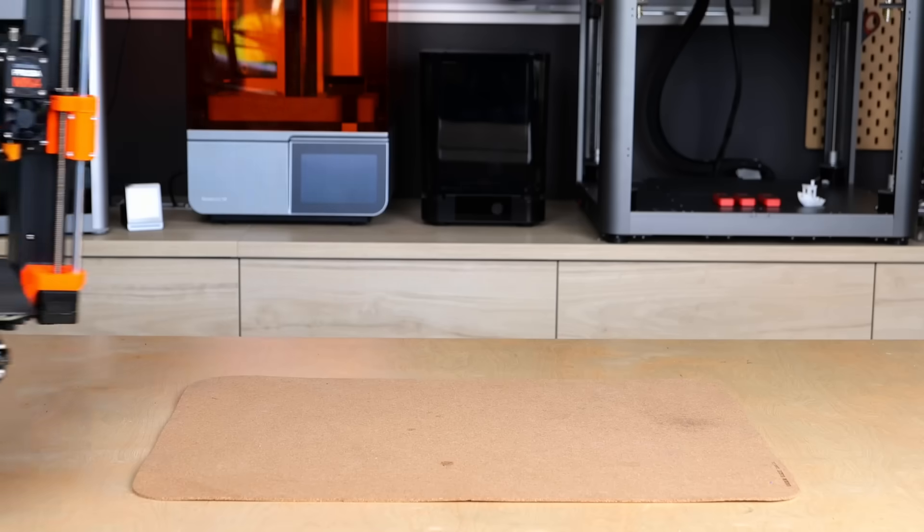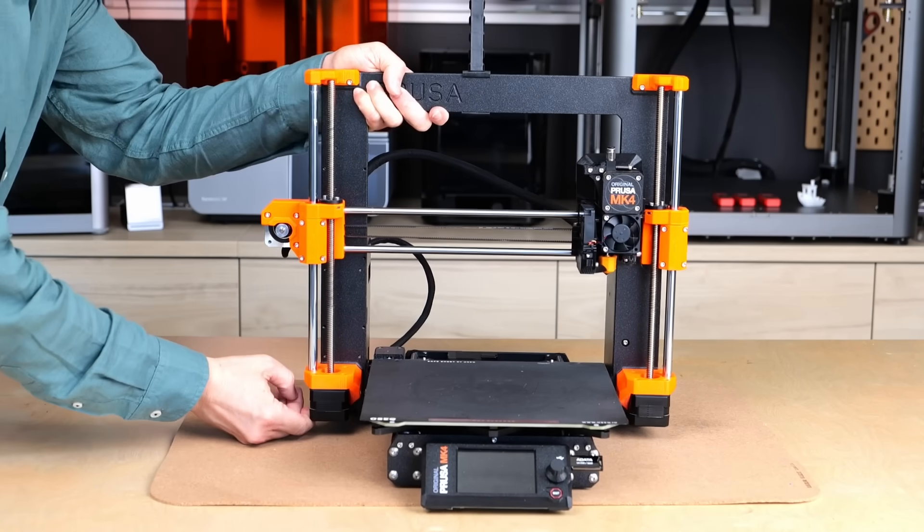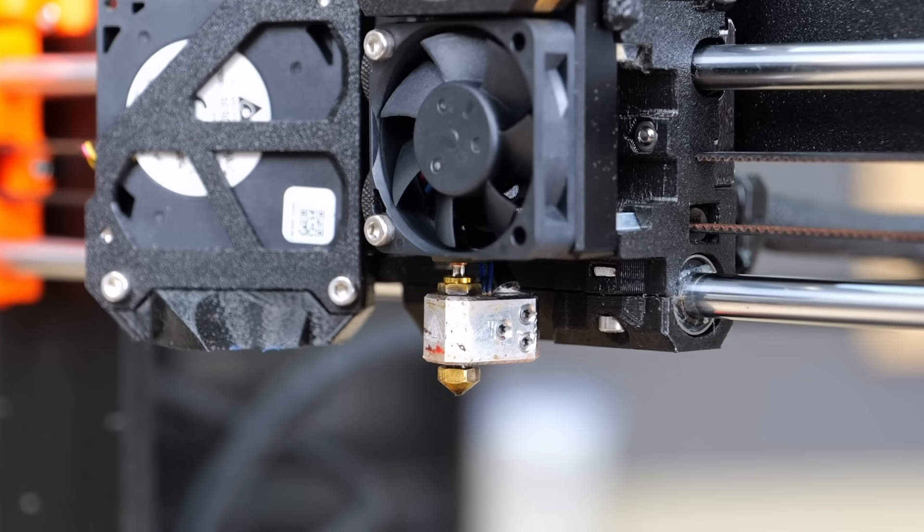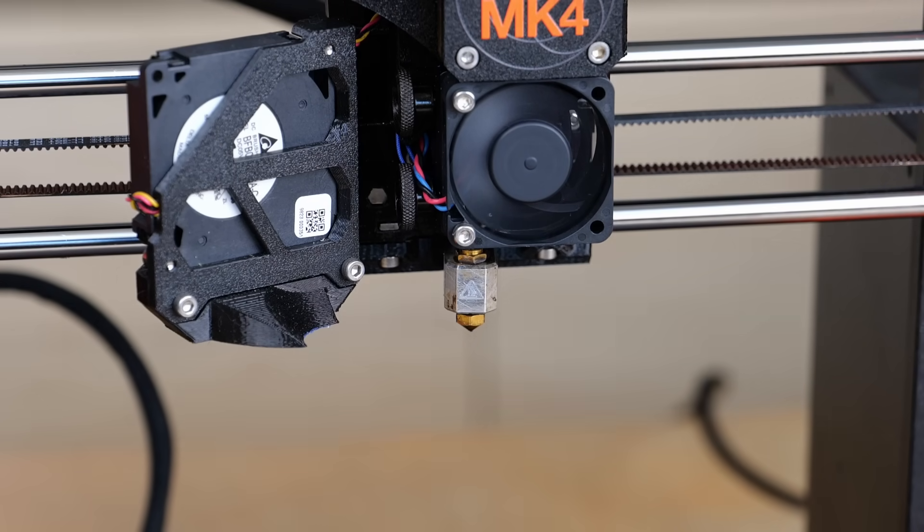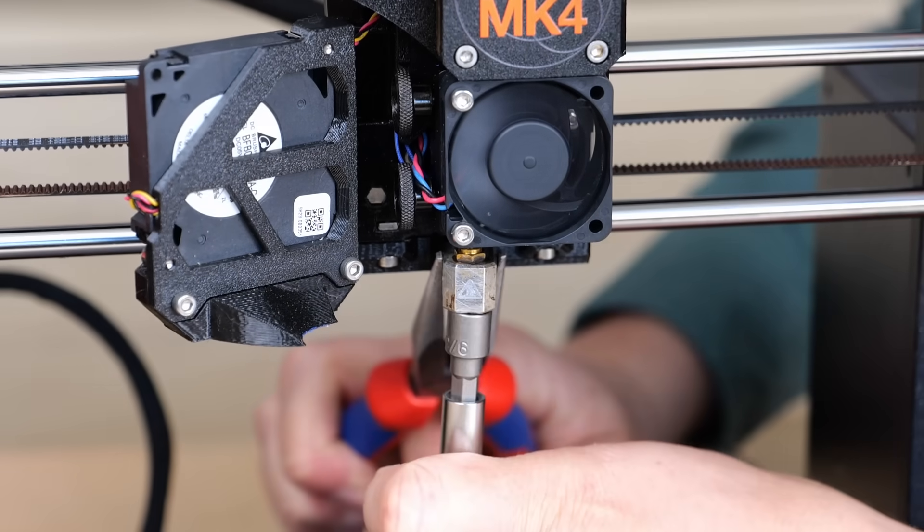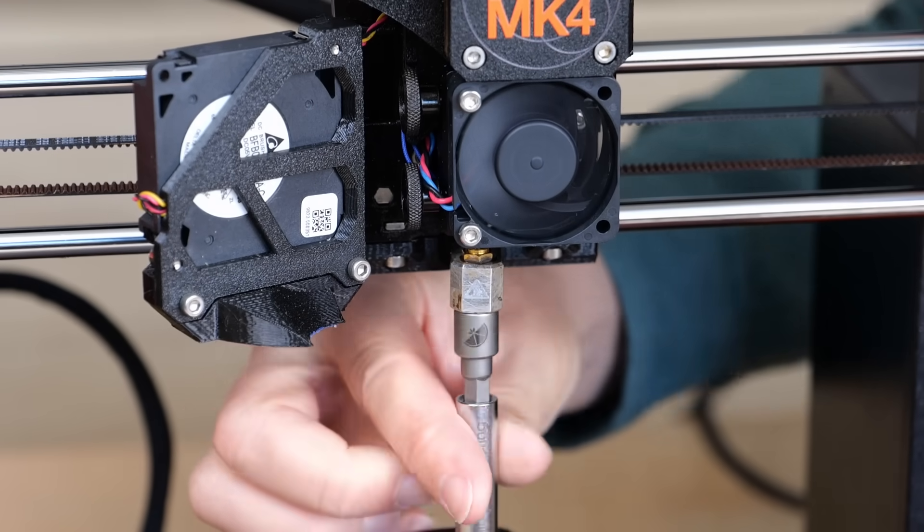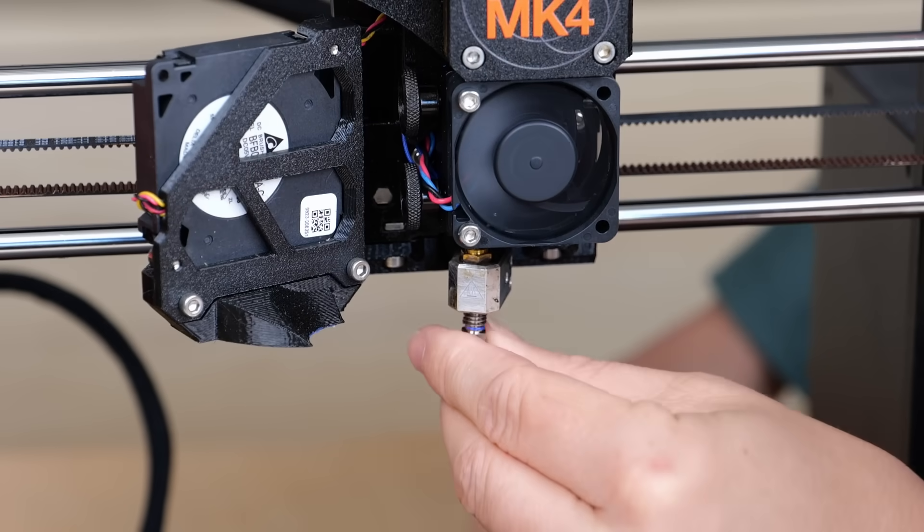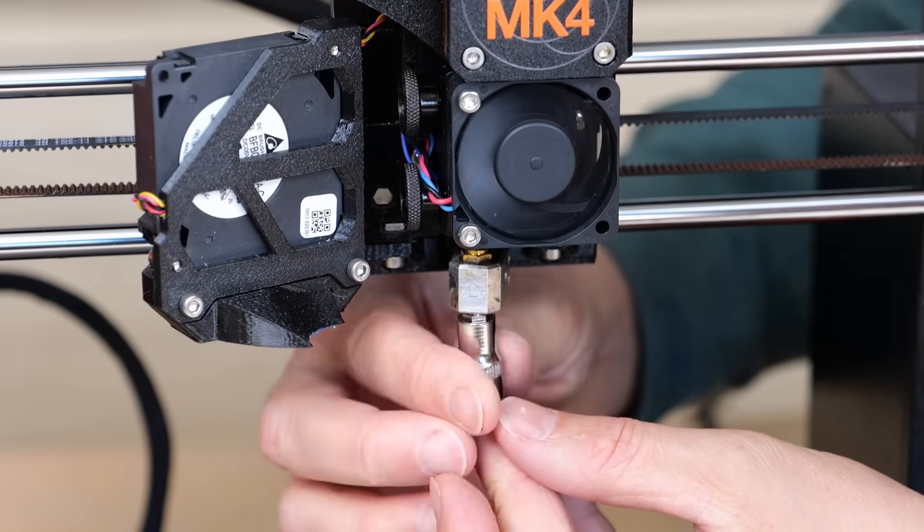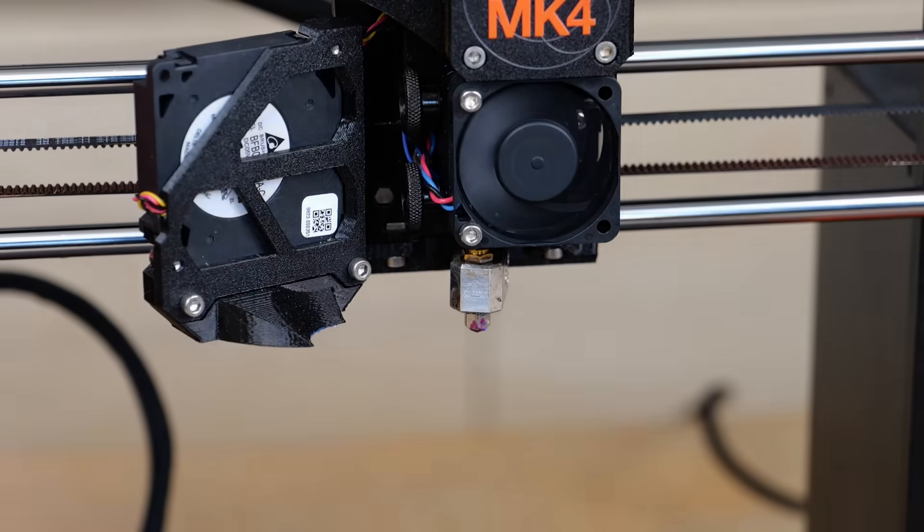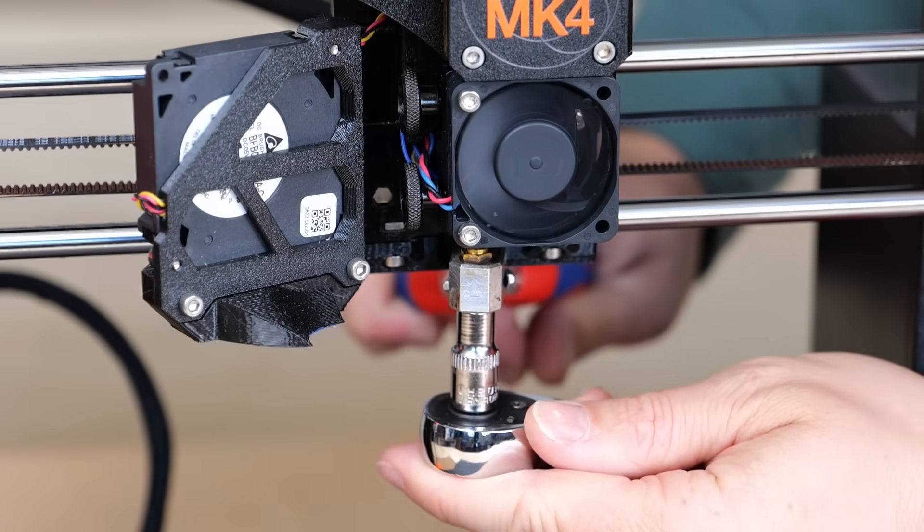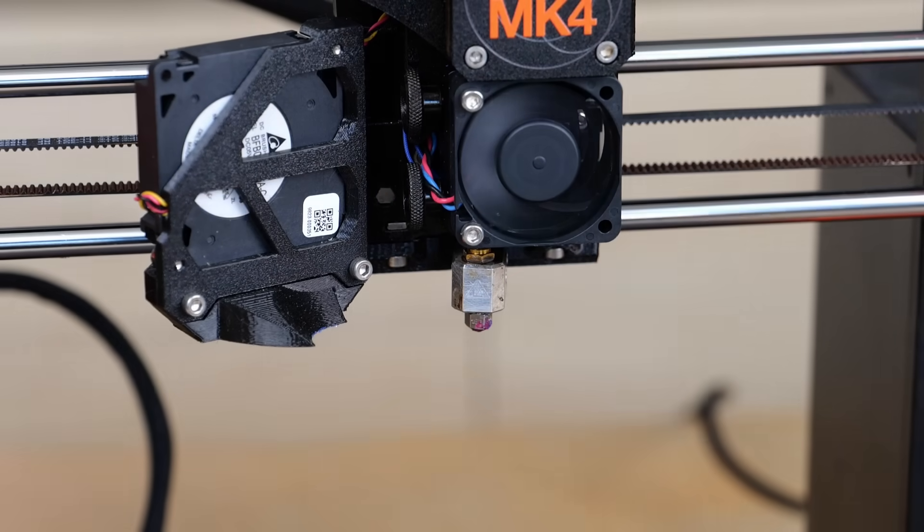So let's get back to injection molding. I first wanted to try this on a very typical 3D printer and chose my Prusa Mark IV. The Prusa has a relatively short hotend, so in its standard configuration it is not able to melt more than around 15mm³ of material. In order to increase its performance a little, I installed one of Bondtech's CHT nozzles, which due to its internal geometry is able to at least double the melting capability. By also increasing the nozzle diameter, we decreased the pressure loss in the nozzle, which should allow us to press the plastic with even more pressure into the mold.